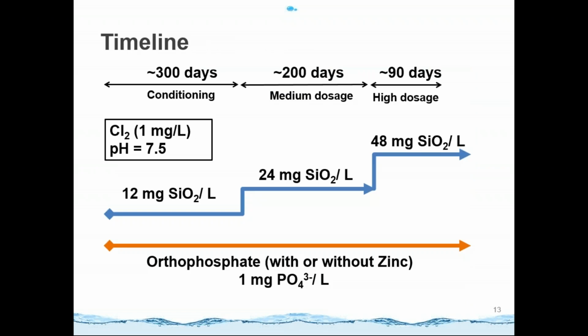So this is the timeline of our experiment. During the experiment, we maintained the orthophosphate treated system at 1 milligram phosphate per liter. Then we used 12 milligrams silicon dioxide to condition the system, and we investigated the medium dosage of the sodium silicate at 24 milligrams silicon dioxide per liter, and we also investigated the scenario at the high dosage of the sodium silicate at 48 milligrams per liter.